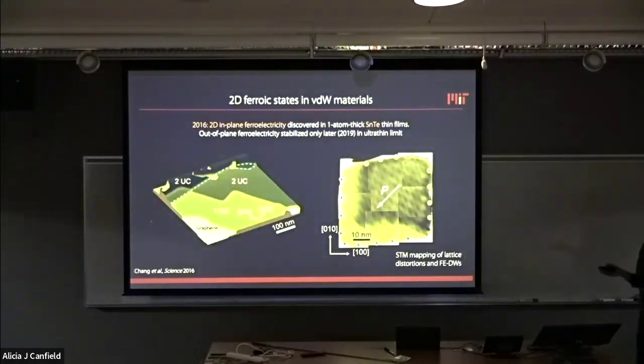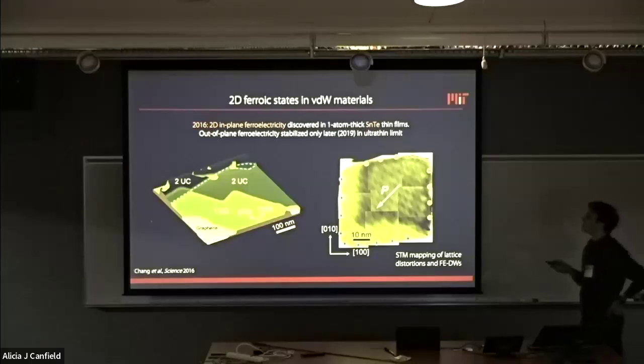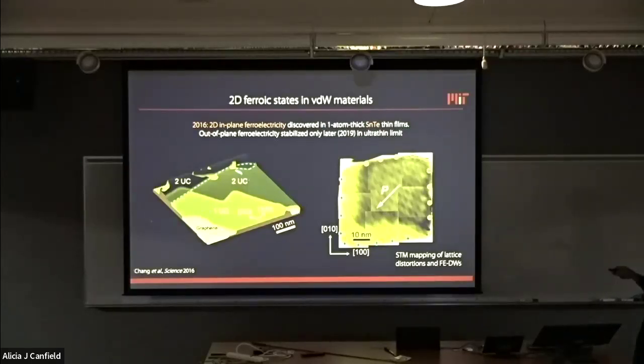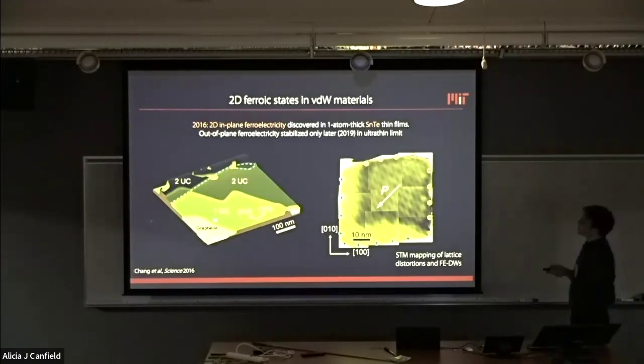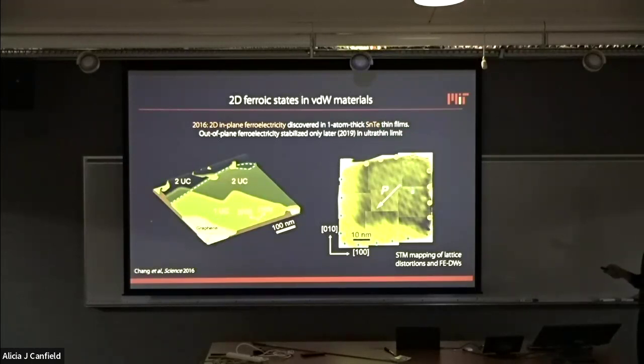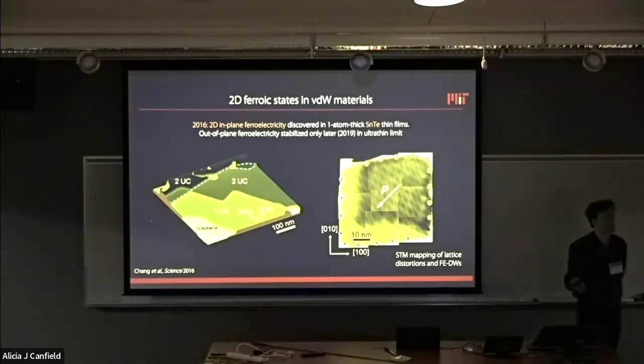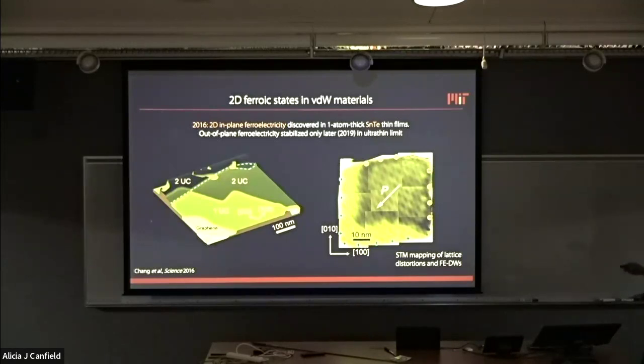So in terms of 2D ferroic states in van der Waals materials, the original discovery that materials down to a single unit cell could sustain long-range ferroic orders is from about 8 years ago, 2016. This is work on tin telluride thin films, which I believe were grown, I'm not sure if by MBE, but anyway, thin films grown on graphene, and what they observed using an STM is that there are actually atomic displacements that generate an in-plane polarization. These 2D ferroelectrics tend to support primarily in-plane polarizations. Out-of-plane fields undergo depolarization effects. And what this STM measurement underscores, which is different from the traditional techniques to probe ferroelectricity, is that it's actually extremely hard to probe ferroic states in 2 dimensions. So sometimes people have to resort to really advanced types of probes.